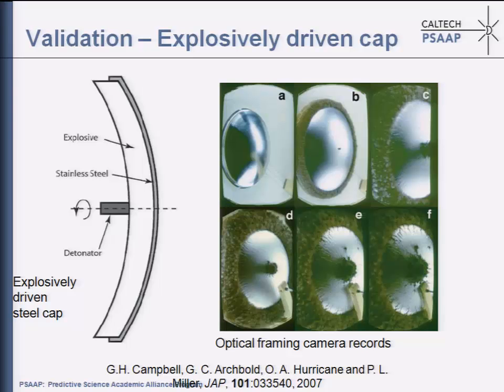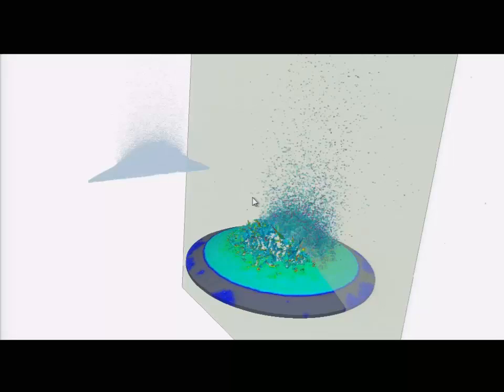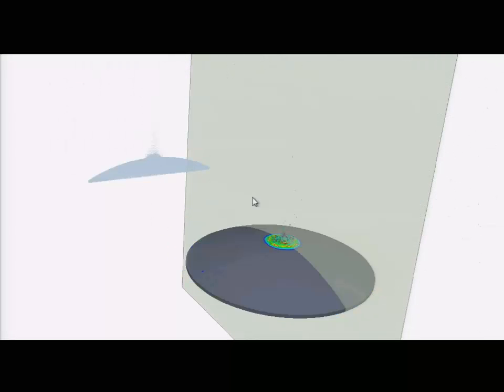And the nice thing is that they showed a lot of pictures of how the process takes place, and they also collected fragments. So they were able to recover fragments and provide statistics of, for instance, fragment sizes. So again, you have a data set that you can compare against to assess predictiveness. So here you have some simulations that we do of this particular type of test. These are supposed to replicate the Campbell et al. test.